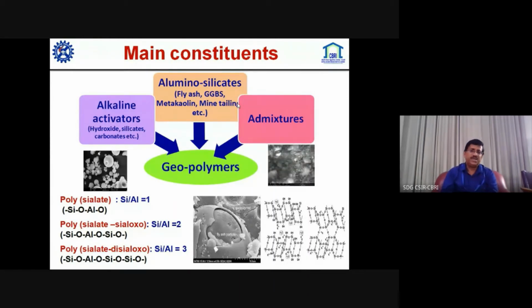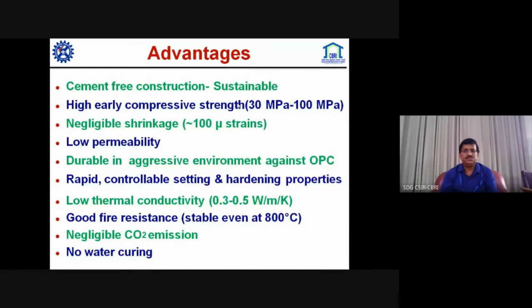Mainly the activators involved are a hydroxide and a silicate. So people generally use sodium hydroxide and sodium silicate for making it. The other ingredients for making a concrete are the same: coarse and fine aggregate. Some admixture is required to modify the rheological behavior, and those have been used and work well. It has a lot of advantages compared to the conventional concrete system.